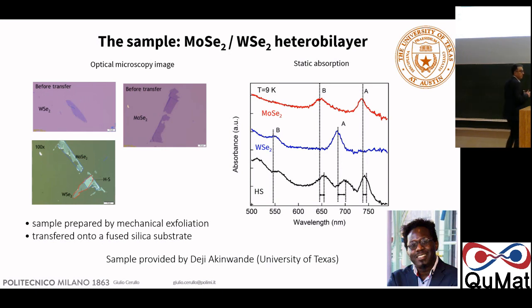And now you can measure the absorption spectra of this material. So you see at 9 Kelvin, the MoSe2, you have the A and B exciton. The WSe2, again, the A and B exciton. Now, if you measure the heterostructure, you see that pretty much you get the sum of the two. So you see the A exciton of one, the A exciton of the other, B and B. They are slightly redshifted because, of course, the dielectric environment changes when you put them on top of each other. But this shows that there is no strong interaction between the two materials, let's say, in the ground state, not excited.